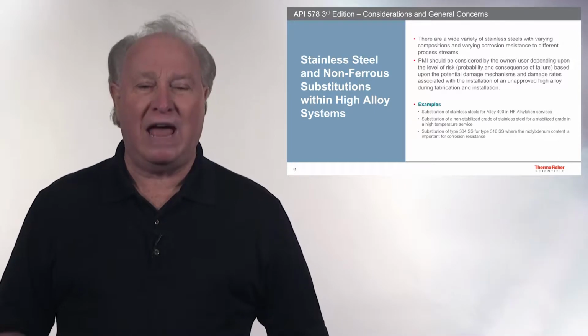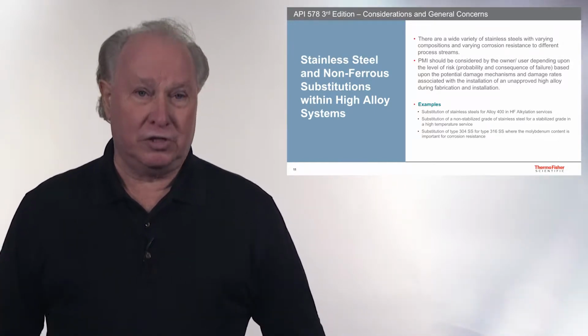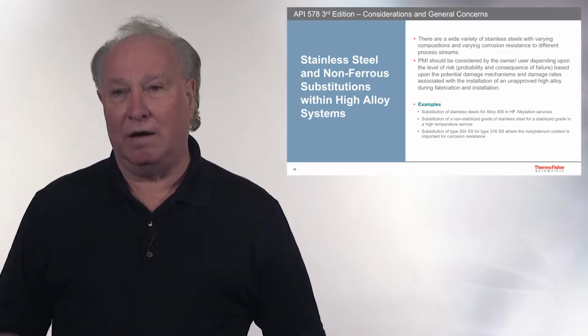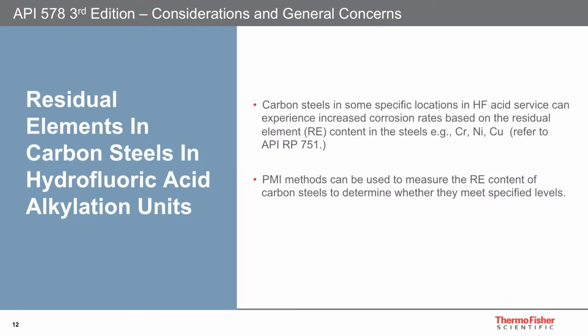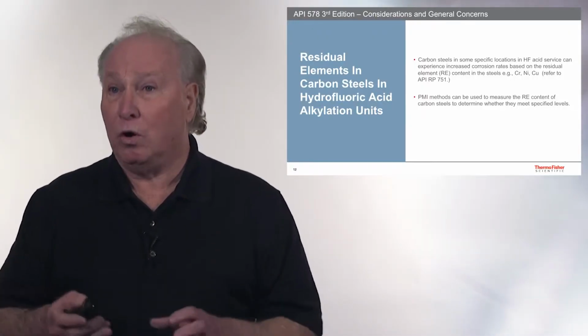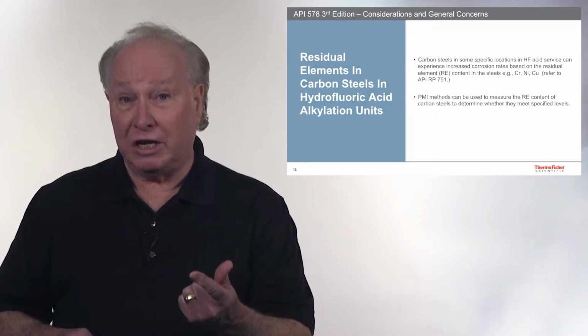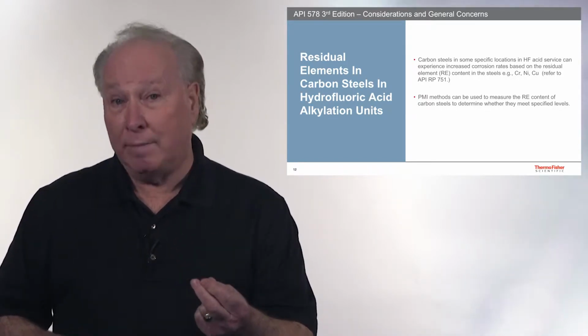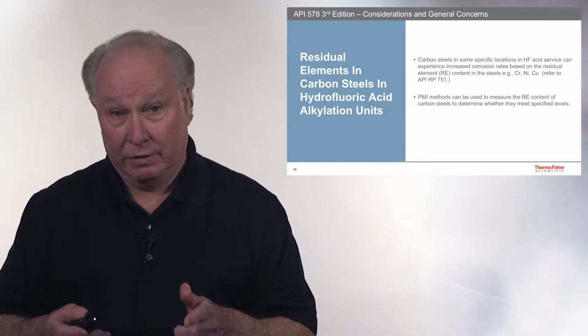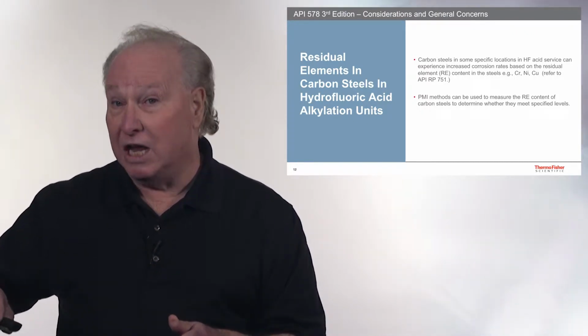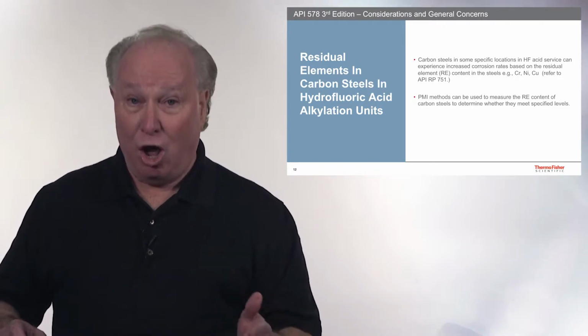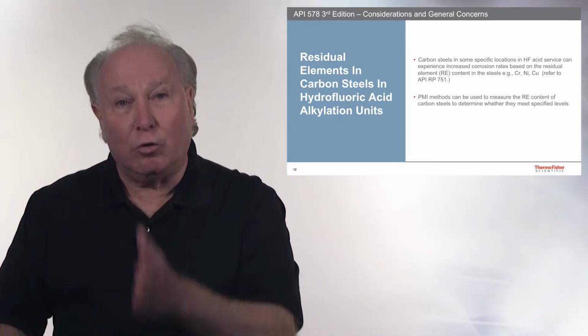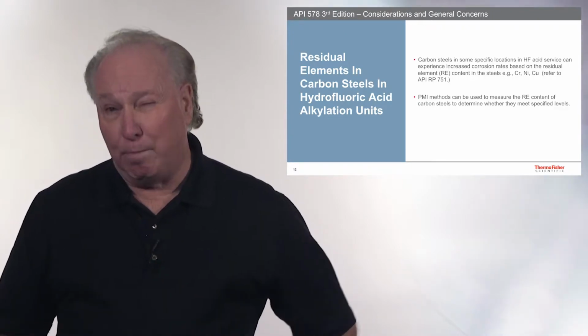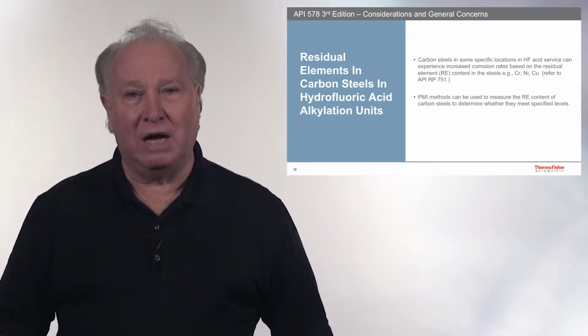The biggest concern that we have is in HF alkylation units. There's another document that we have for that called API 751, and that's really corrosion problems based on residual elements. Residual elements are things that are left over in the heat and the pour of the metal, and like chrome plus nickel plus copper needs to be nominally 0.15% combined. But if you have one that is, say, 0.25% and one that's low, and you weld those together, you get corrosion right in that area. Those are big concerns throughout our industry to minimize this corrosion risk.